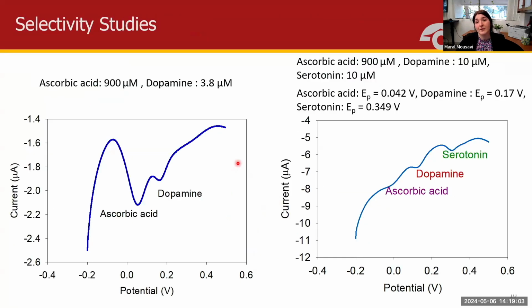So typically we study selectivity, which is determined by the chemical properties of these neurotransmitters themselves, but also by how we functionalize and control the surface charge of the electrodes. We've done selectivity studies in cerebrospinal fluid. You're noticing that typical interference that comes from ascorbic acid is not an issue for this study, and we can separate these peaks, for example, dopamine, serotonin, along with ascorbic acid that's present in most tissues.